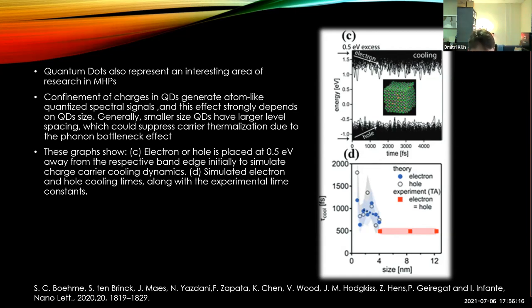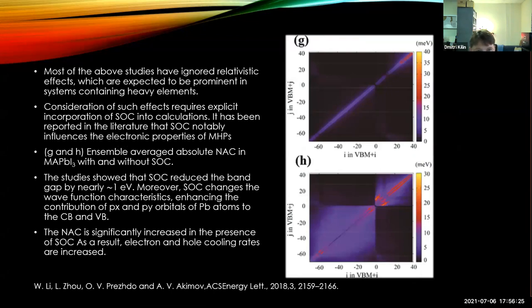And any interaction, including spin orbit interaction, does it bring levels closer or does it repel them? If you just solve for a two-level system with an off-diagonal element, does any off-diagonal interaction make levels closer or pull them away from each other? Further. Okay. And then the next chain, relaxation between denser orbitals or sparser orbitals is quicker? Denser orbitals are quicker. Okay. So it looks like if the spin orbit coupling splits the levels in the valence and conduction band further away from each other, if they're already sparser due to quantum confinement, spin orbit coupling makes them even sparser, and it is expected to slow down the relaxation. Mm-hmm.